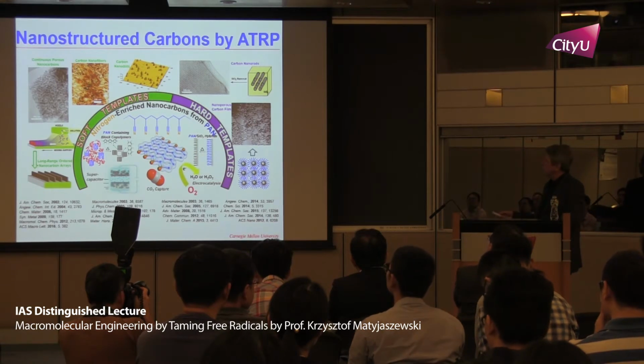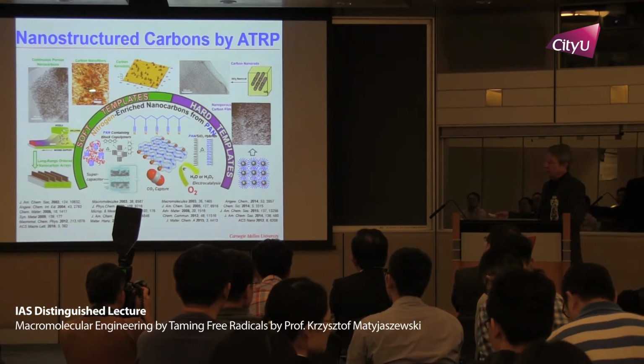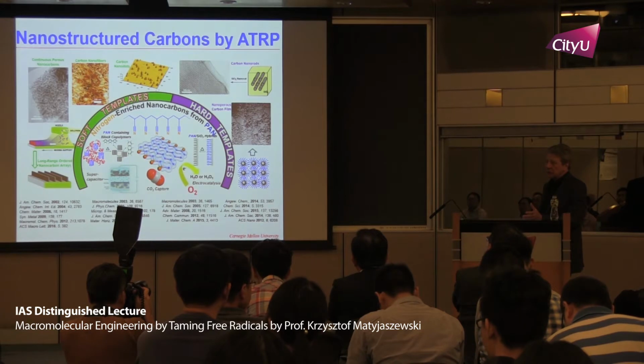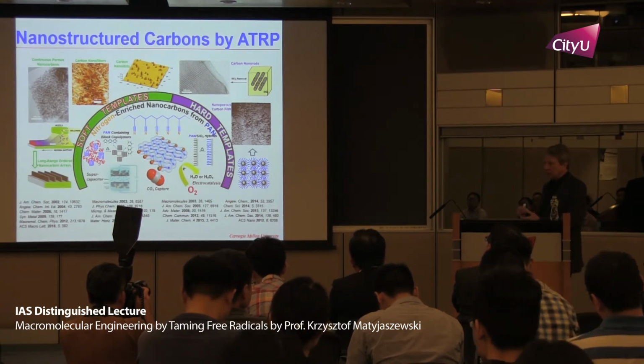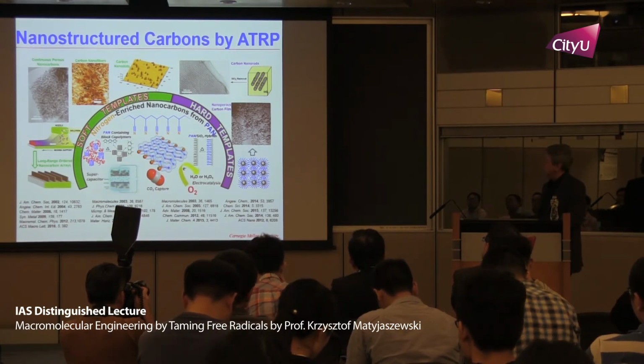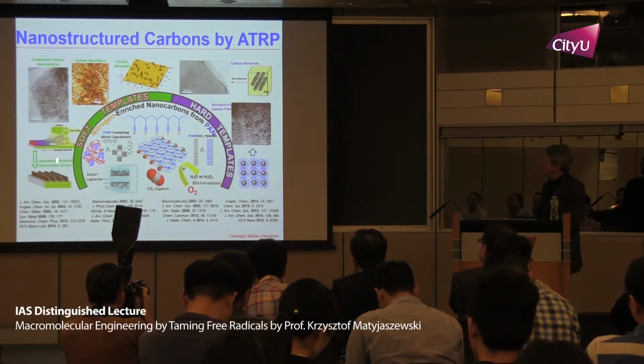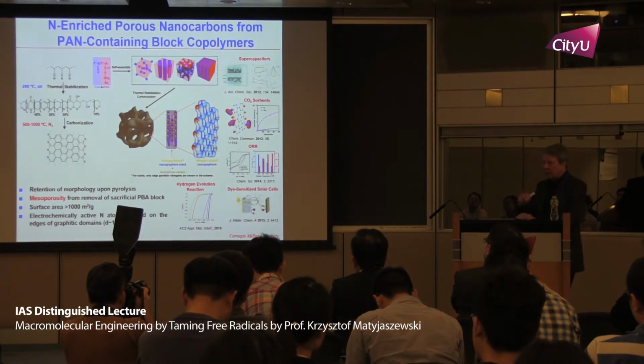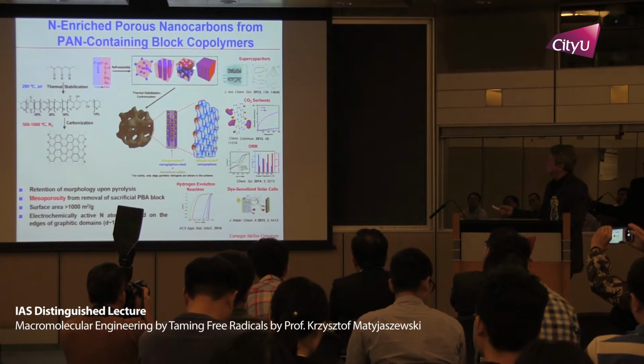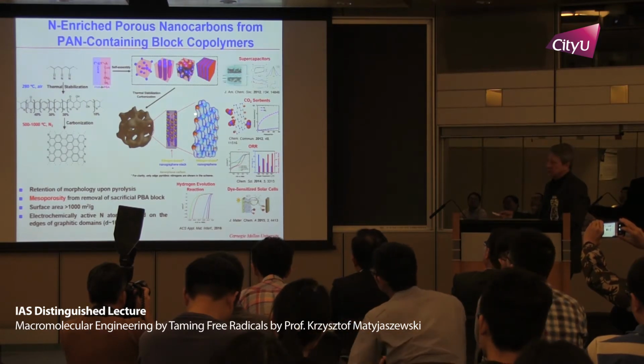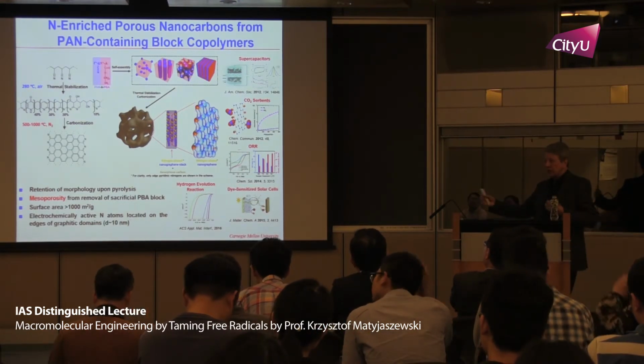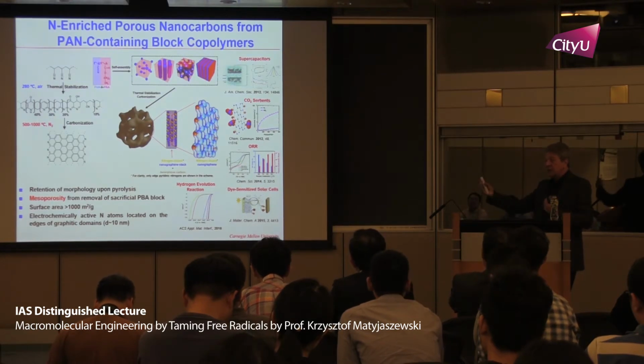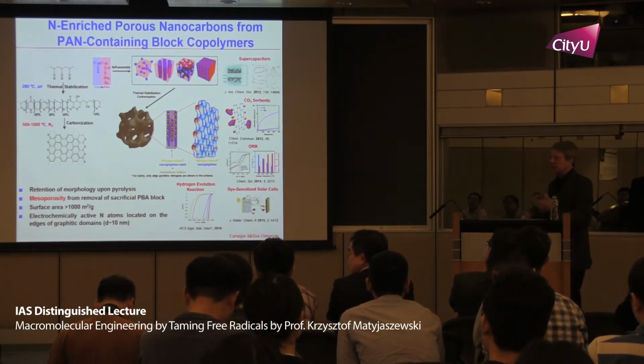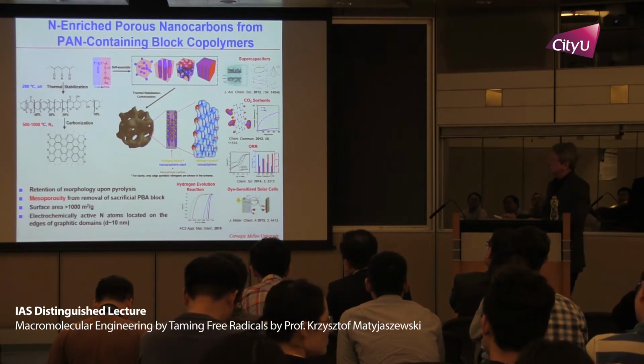You can do the same, in fact, also using soft templates. So this is based on block copolymers. We are using typically polybutyl acrylate and polyacrylonitrile, and can have lamellae, can have also cylinders and spheres, and you can play with the whole range of morphologies. One of the most interesting, in fact, is the gyroidal system, because it's bicontinuous. And it is bicontinuous with good connectivity on a distance of tens of microns or even hundreds of microns.